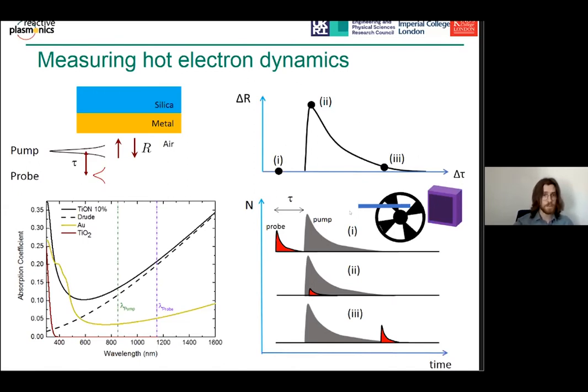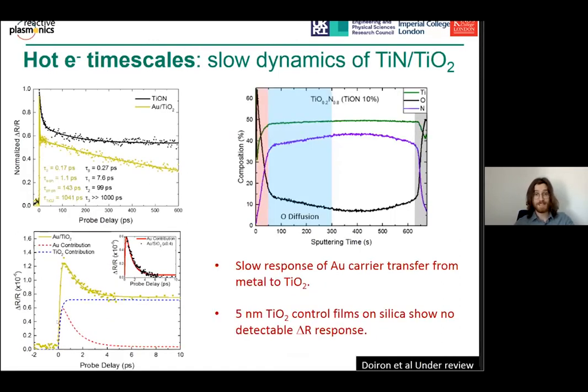So in this experiment, we compared gold with titanium oxynitride, and we were interested in injecting hot electrons into titania. So we made sure to excite these at wavelengths that don't excite any hot carriers in titania. This is just an animation of the pump probe. So with the titanium nitride, what we found very interesting is that they have these incredibly long hot electron lifetimes. So typically in a metal, we have hot electrons on the lifetimes on the scale of picoseconds, as we see in the gold down here. However, with the titanium oxynitride, we have these long lifetimes, up to a nanosecond. And we were aiming to understand why this was occurring.